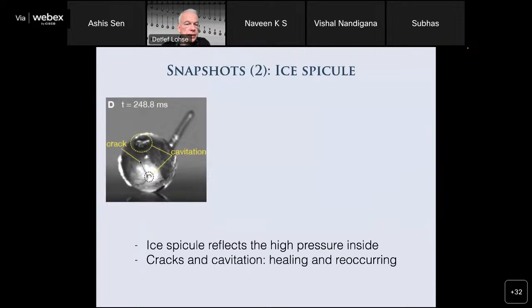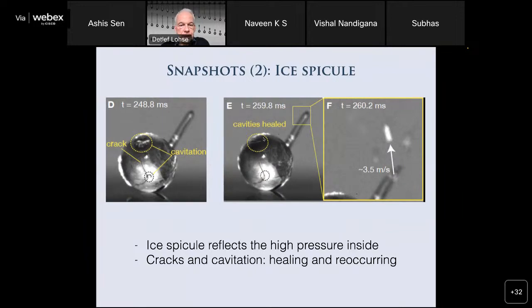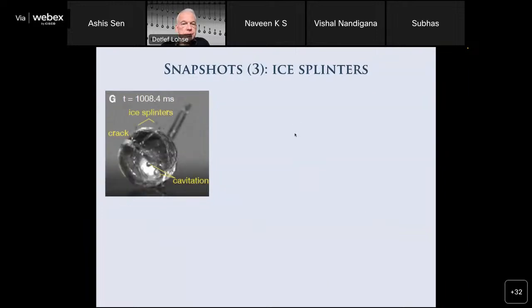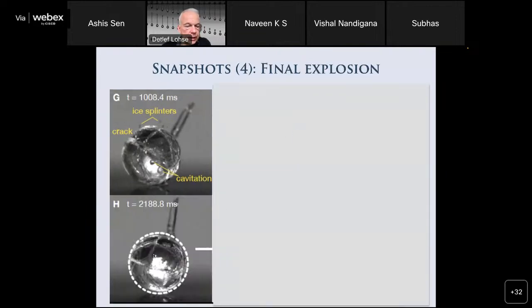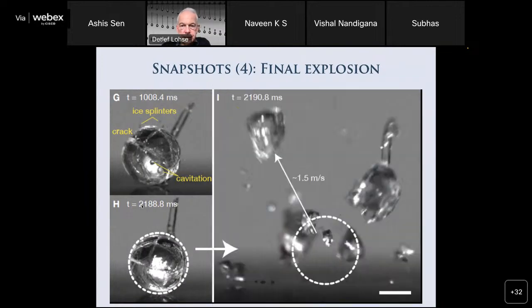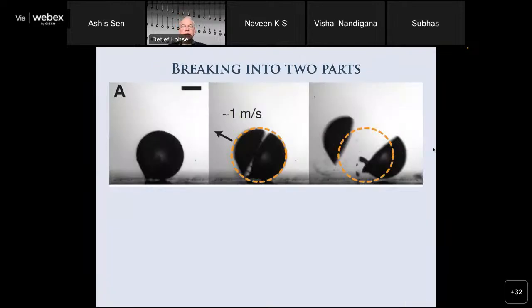From time to time you get some crack, but this heals again. And then it further freezes, and the pressure inside gets larger and larger and larger. So these spicules grow, but the pressure at some point is so large that things will explode. And this is what you see here. Here you see the ice splinters, and now finally, after 2 seconds, it's fully frozen, and then the pressure is so high that the whole thing explodes, which you see here. Often it breaks into 2 parts, which you see here.